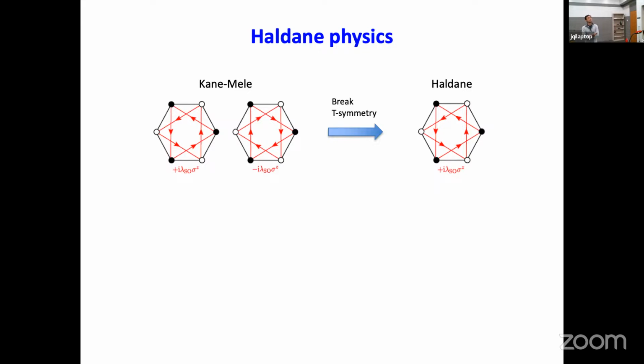And yes, we also check that the spin quantization axis is really out of plane by applying an in-plane magnetic field. And so it actually agrees quite well with the expectation that we get a quantum spin Hall insulator described by the Kane-Mele model before time reversal symmetry is broken. So one question we have is, can we just break the time reversal symmetry by applying a small out-of-plane magnetic field, then reduce the system to a Haldane Chern insulator?